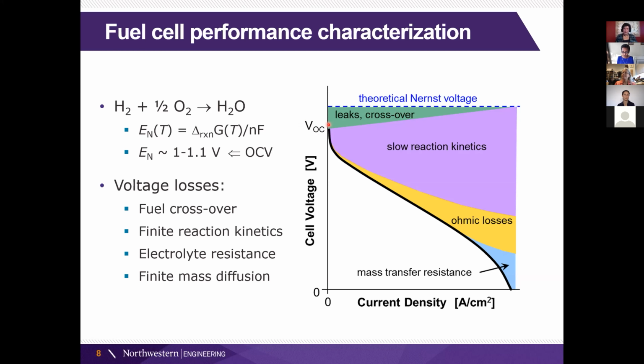Then, as we start to draw current, we see the consequence of various loss mechanisms. First of all, we may even have a little bit of a leak or crossover such that we don't actually get the ideal open circuit voltage. As we start to draw current out of our system, initially we see a decrease because of slow reaction kinetics. These are what are called the overpotentials at the 2 electrodes. Then we start to see the impact of the resistance of the electrolyte itself, a linear regime that shows up, which is our ohmic losses. And if we go to very high current densities, we're not able to deliver the gases into our fuel cell as quickly as we're trying to extract current out of it, and we start to see what are called mass transfer resistance losses. So this is the voltage.